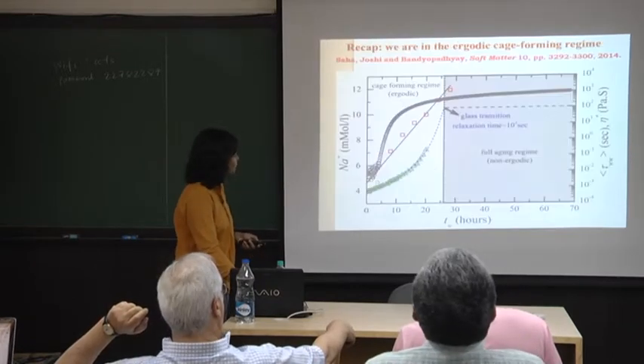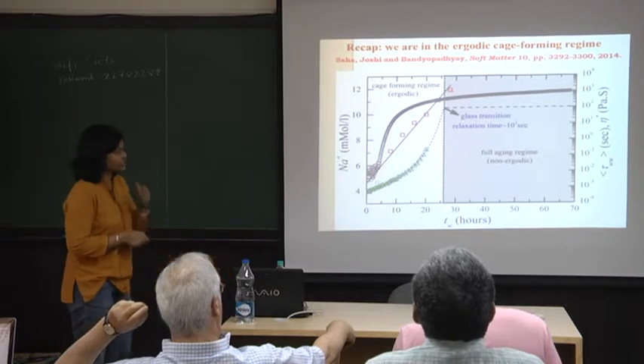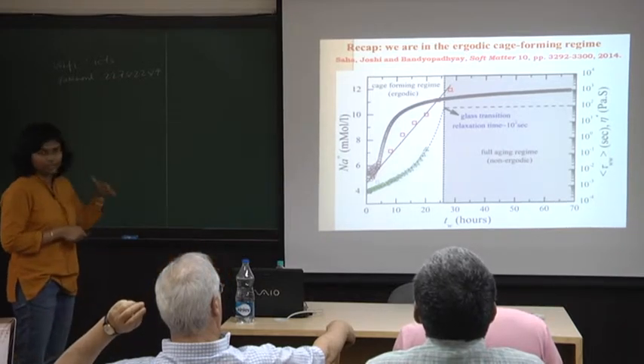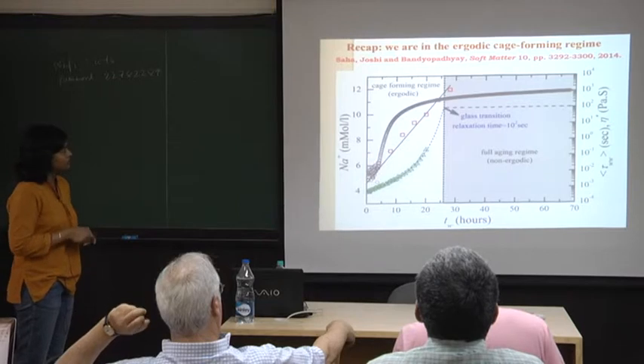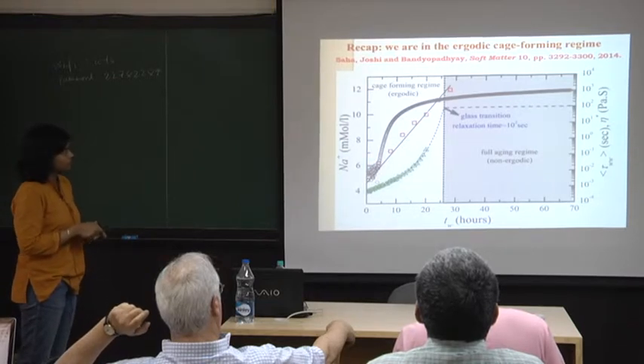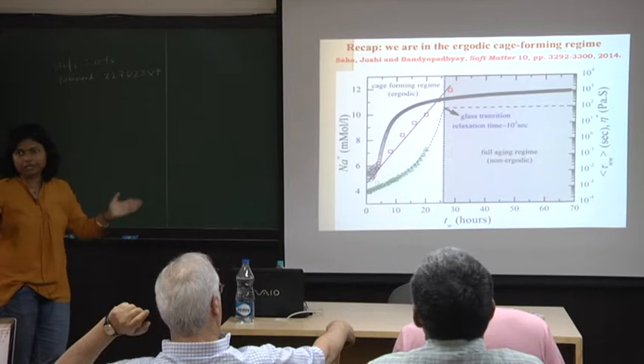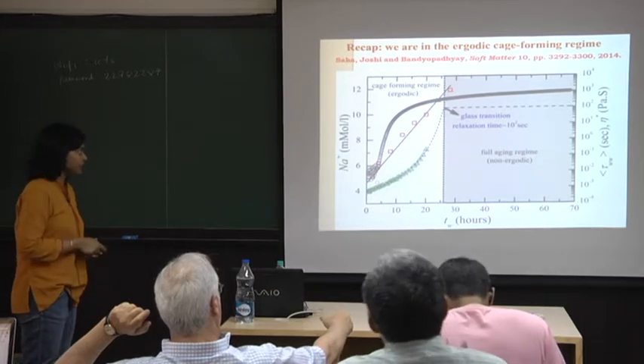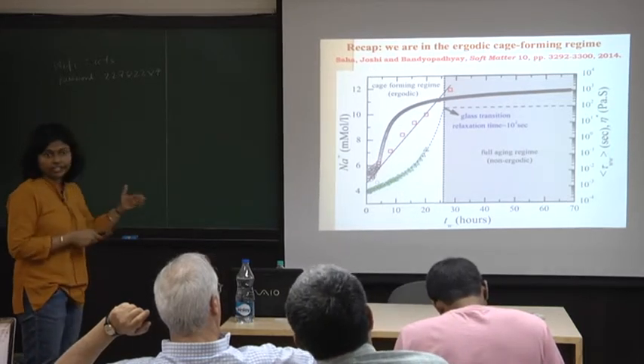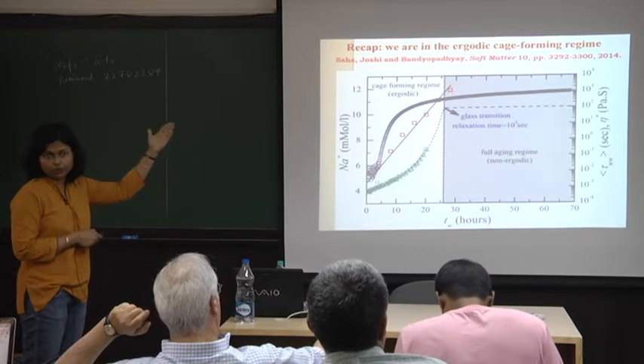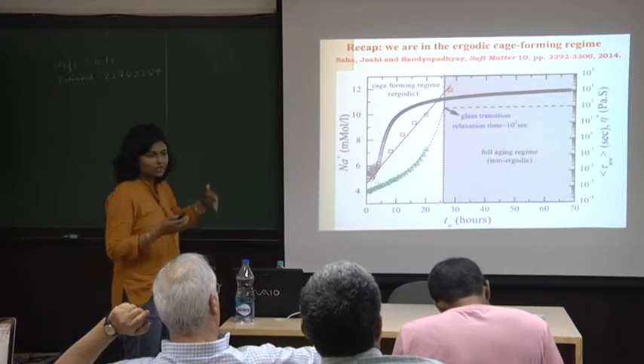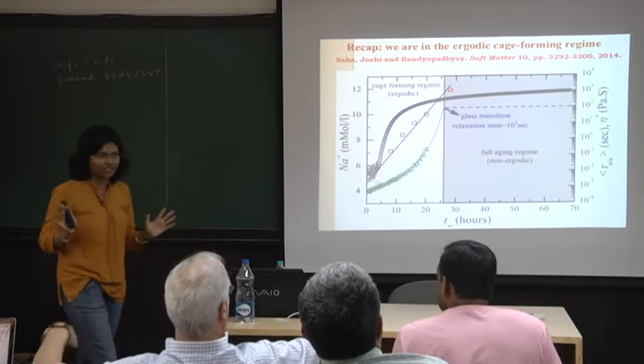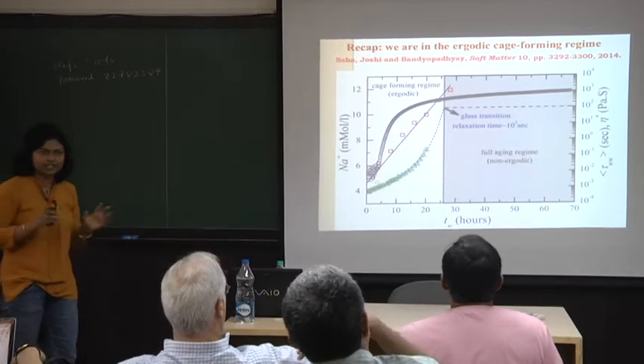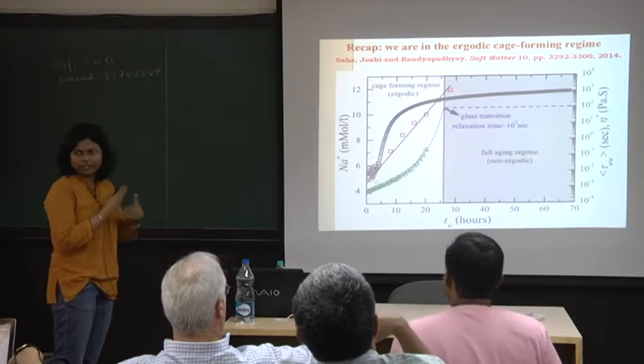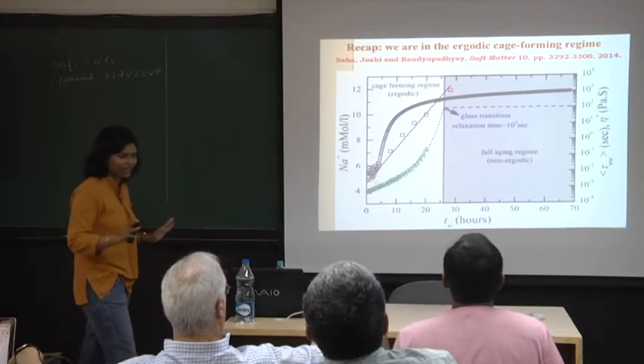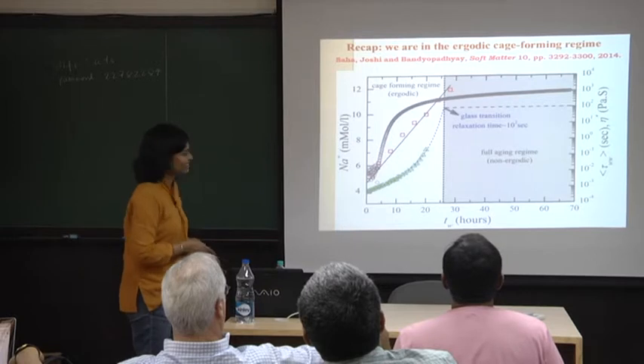I'll have to do a lot of skipping, so I'll also skip this. Just to recap what we saw and what we did: this is the measurement of the sodium ion concentrations coming out of the particles versus the age of the system. Fortunately for us, we can do this even beyond what we are calling the glass transition time, which here is 100 seconds, which I totally agree is arbitrary and therefore meaningless. However, when we measure time scales that are far, far away from that, we decided to go with the 100 seconds.